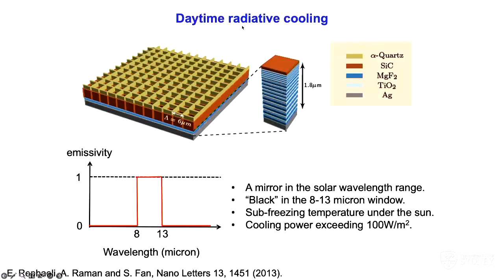Together with Eden Rephaeli and Aaswath Raman, we wrote this theoretical paper. We designed a photonic structure that has an emissivity spectrum that looks schematically like what I show. We did some calculations to show that if you build a structure like this, you should be able to get sub-freezing temperature under the sun. In other words, at an ambient temperature of about 30 degrees Celsius, if you build the structure and do it right, you are going to see a temperature below 0 degrees Celsius passively. And the cooling power exceeds 100 watts per meter squared. So that was the theory we did.